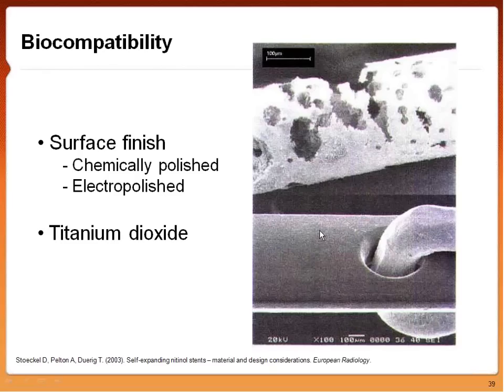The beauty of Nitinol is that having a thin titanium dioxide layer is what makes it biocompatible. Usually the layer is between 50 and 80 angstroms thick, but it's that layer that allows your device to function within the human body. So using these two different processes, we can get a better surface finish. The picture here is of a device that was implanted with a thick oxide coating and hadn't been surface treated, and you can see how much it's corroded inside the human body. Here we have a wire that was electropolished. You can see the difference between the two after explant.